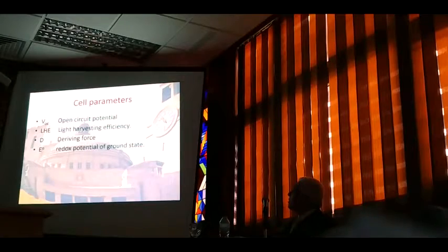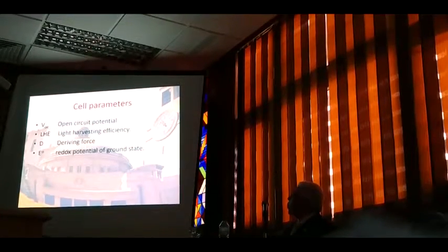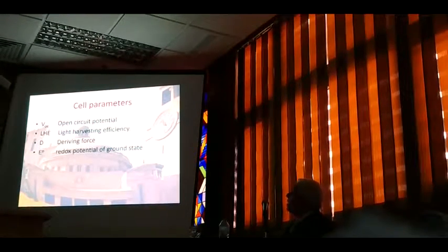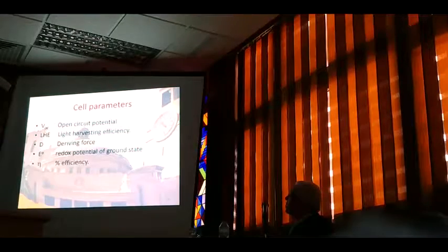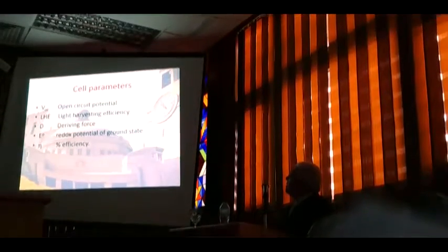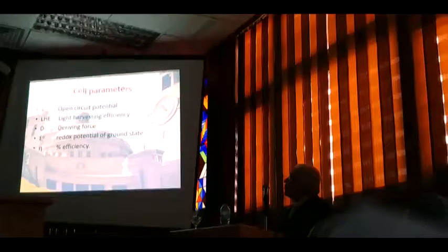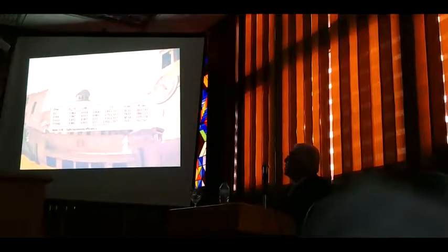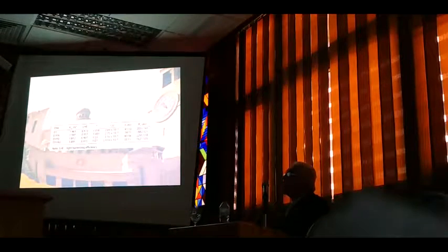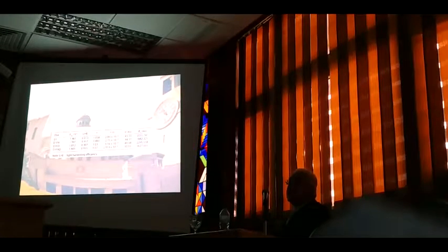We can calculate all these quantities: open circuit potential, light harvesting efficiency, driving force, reduction potential, percent efficiency of the dye. We did calculate this for the dyes we did, and these are the numbers. So we can provide the experimentalist a first-hand account of what to prepare and what to skip.